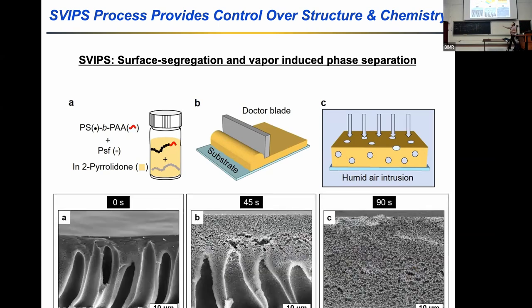And we see that. If I expose it to the humid environment for 0 seconds and plunge it directly into DI water, you have these large macro voids that aren't that useful in the context of creating a lot of surface area per volume. At 45 seconds, you begin to see this lacy, spongy-like structure that we want, but at the end, there are still these macro voids. At 90 seconds, we've given the polymer material enough time to phase separate, and the slow solvent-non-solvent exchange creates the desired nanostructure across the whole thickness.